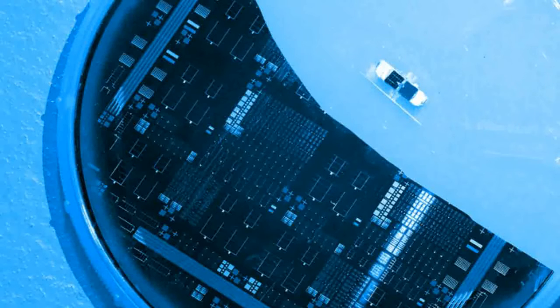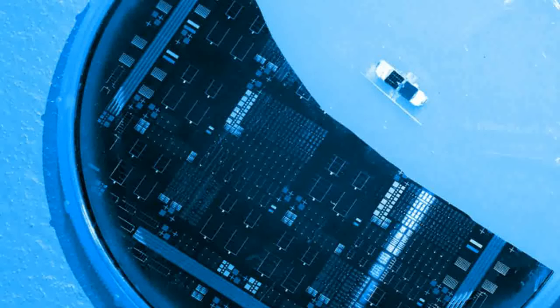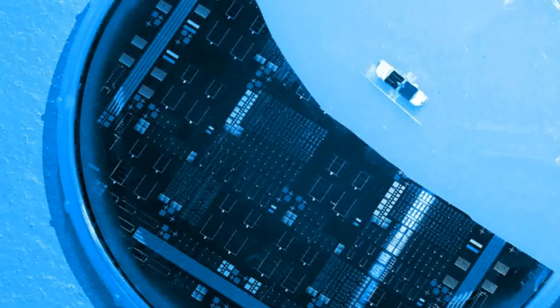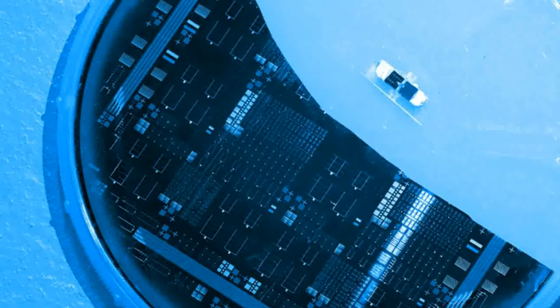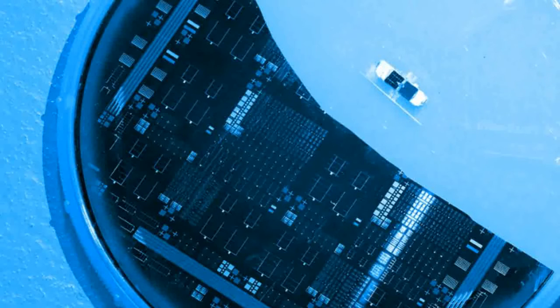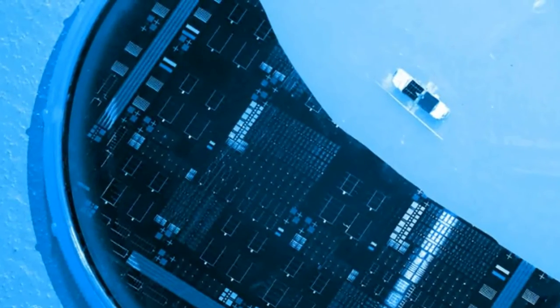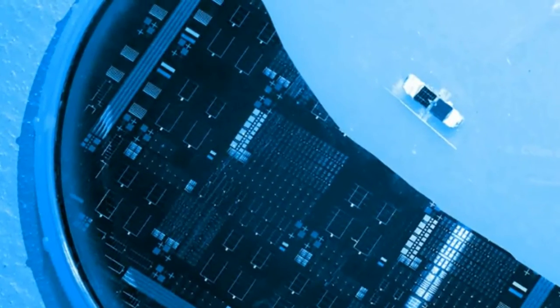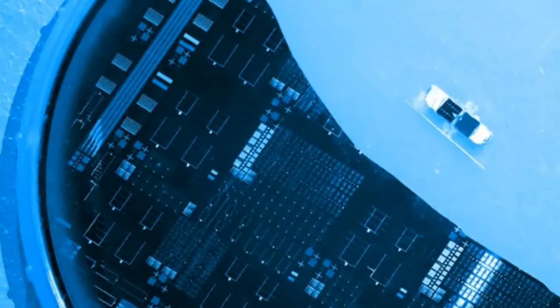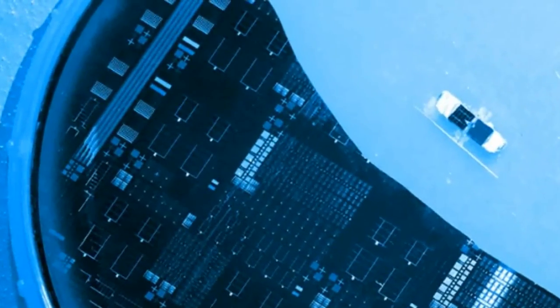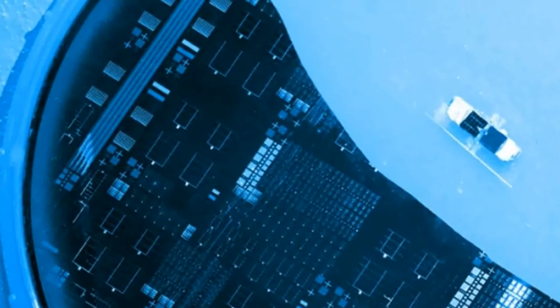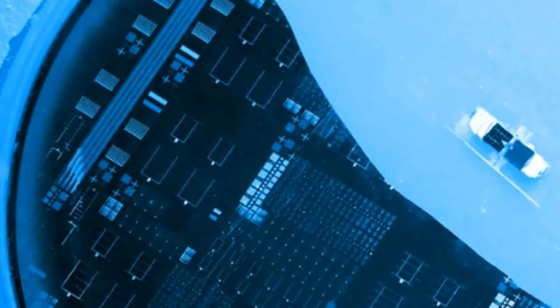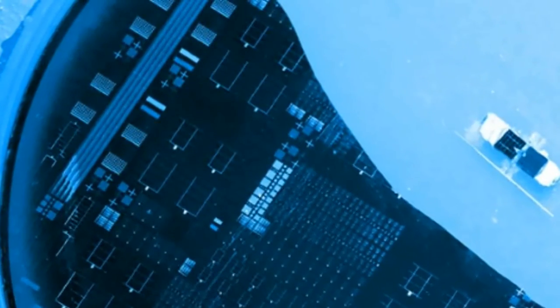This intentional step design allows the top gallium arsenide phosphide layer to absorb the high-energy photons from blue, green, and yellow light, leaving the bottom silicon layer free to absorb not only lower energy photons from red light transmitted through top layers but also the entire visible light spectrum. The unique design ensures that the silicon cell below can receive more photons in the exposed step part, increasing the solar cell's efficiency.